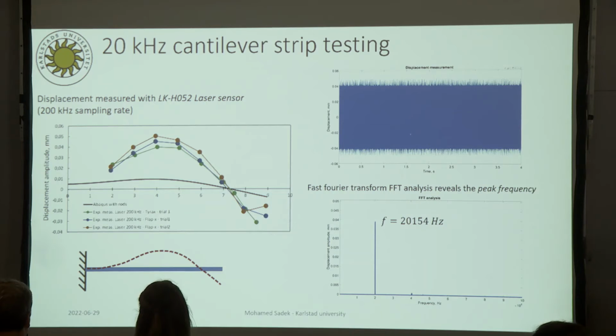Here's the laser measurement that we did of the amplitude along the specimen. Up to the right, you see how the signal looks, and doing fast Fourier transform analysis reveals the frequency of the signal, which is 20 kHz. That is correct, measured experimentally. The sampling rate is 200 kHz from the laser, and the results were not as good as we hoped for. We have huge, large discrepancies between the FEM model and the measured displacement with the laser using the first setup.